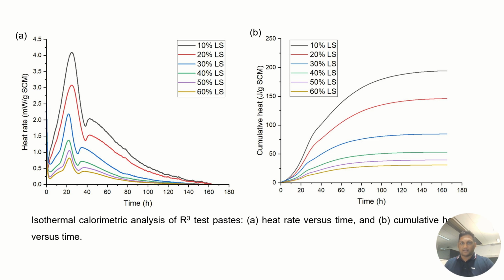Thirdly, the dormant phase is accelerated by the amorphous silicate phases of the pozzolan to form calcium silicate hydrate at 20 to 22 hours, and then the deceleration phase. In this study, the primary hydration peaks of 30 to 60% lithium slag are slightly delayed compared to the 10 to 20%.